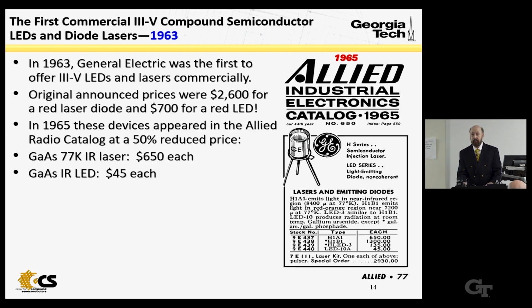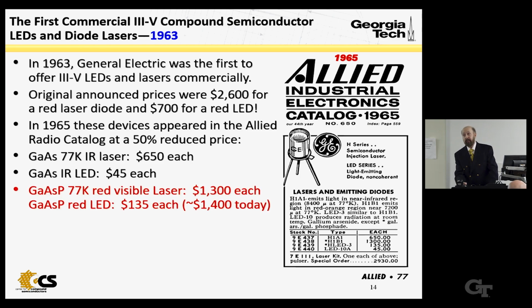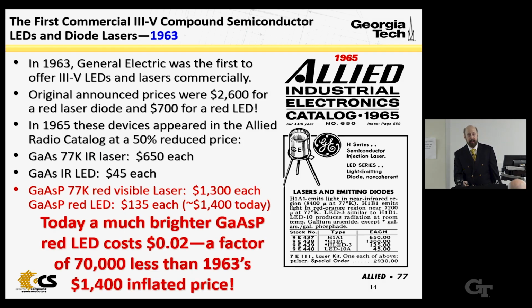So you could buy an infrared laser diode for $650 and an IR LED for $45. Visible laser, again, only operating at 77 Kelvin, was $1,300, and a red LED was $135 each. Corrected for today's inflation, that's $1,400 in today's money. Today, a much brighter gallium arsenide phosphide LED costs about 2 cents, a factor of 70,000 less than 1963's $1,400 inflated price. They still make gallium arsenide phosphide LEDs today for the really cheapest possible applications.